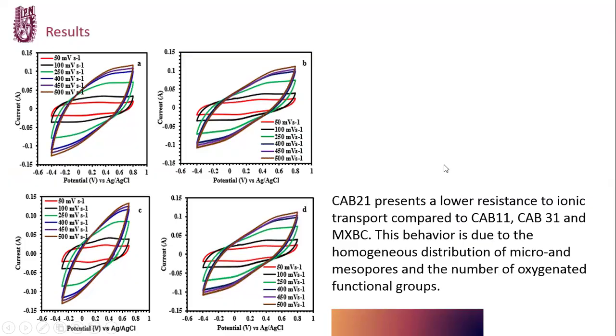The cyclic voltammogram curves of the carbon materials at different scanning speeds are shown in this slide. From them, we can understand that the presence of oxygenated functional groups increases the wettability of the electrode surface and improves electronic conductivity. With increasing sweep speed, the current densities increased, and simultaneously the CV curves gradually slanted, which is related to the fast migration of ions between the electrolyte bulk and the double layer in the electrode.